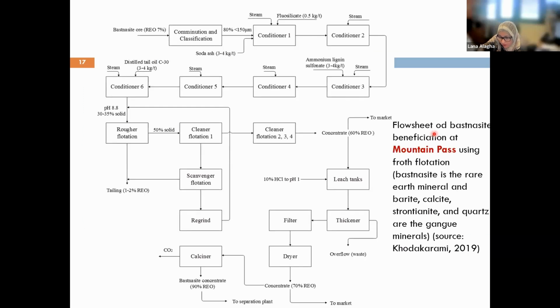Here is a flow sheet showing the beneficiation at Mountain Pass in California. Usually, the Mountain Pass is currently mined using the conventional open pit method. The concentrator flow sheet includes crushing, grinding, and then 6 stages of conditioning, as you can see here. During the conditioning stage, you add your collectors, you add your dispersants or depressants. Depressants are added to inhibit the flotation of the minerals that you don't want to float, like, for example, silicate minerals and other material that you don't want your concentrate to be contaminated with. And this is done under steam to improve kinetics and improve the interaction between the collector and the mineral surface.